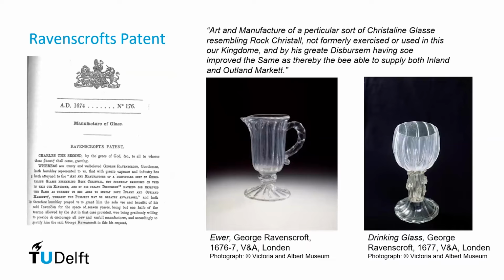And what was already known in the past is that the ratio in which these elements are added determines if a glass is stable or unstable. So the main factor determining glass stability and its tendency to degrade is the composition of the glass itself.